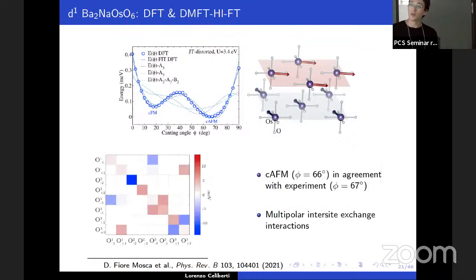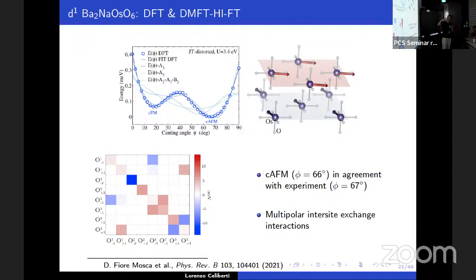With the same kind of calculation, they calculated the multipolar couplings. Here you can see this strong quadrupole interaction, and also some small dipole-octupole interaction. So this canted phase is driven both by the Jahn-Teller distortion and these higher multipolar interactions.